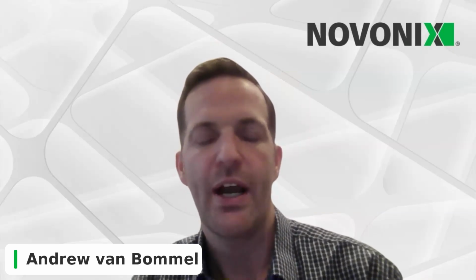Thanks, Andrew. Just a couple more questions. Do you have capability to do 3 electrode measurements? Yep, we do. We have done 3 electrode measurements. We use copper wire in the electrode stack, and then that's slightly plated with lithium to provide the lithium reference electrode for those 3 electrode measurements. And if you want more data on that, you can reach out to us.